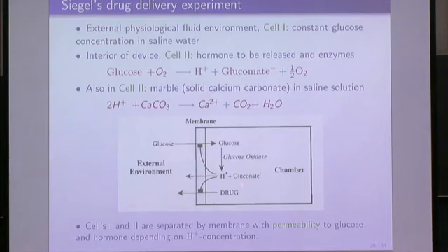However, this is not permanent, meaning that they start diffusing out. When enough of them have left, then again the negative charges that the cartoon I showed you before start becoming active. There is repulsion, and the membrane swells again. As soon as the membrane swells, you have the glucose coming in again, and everything starts up.